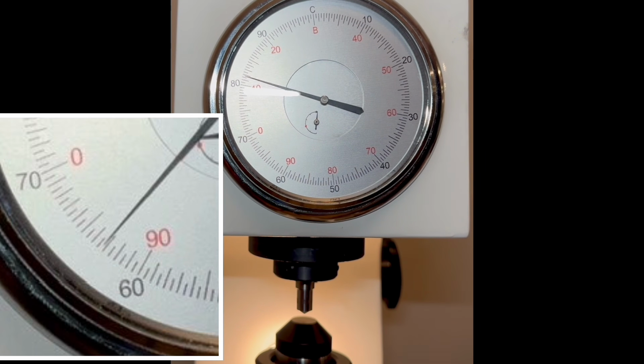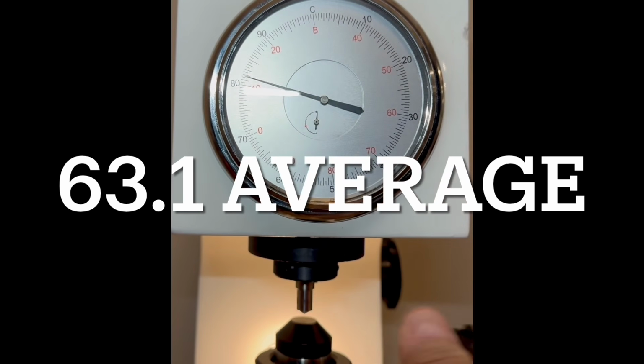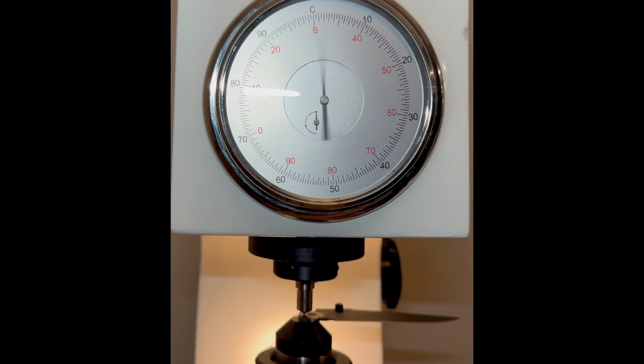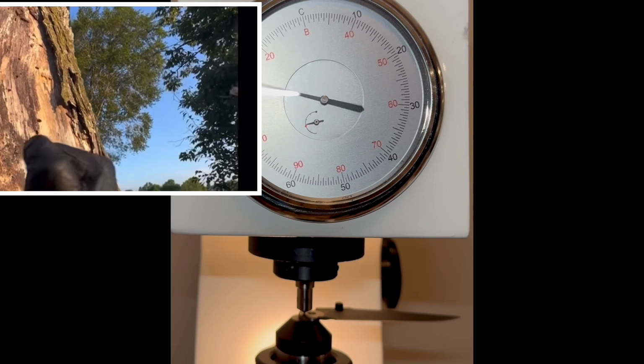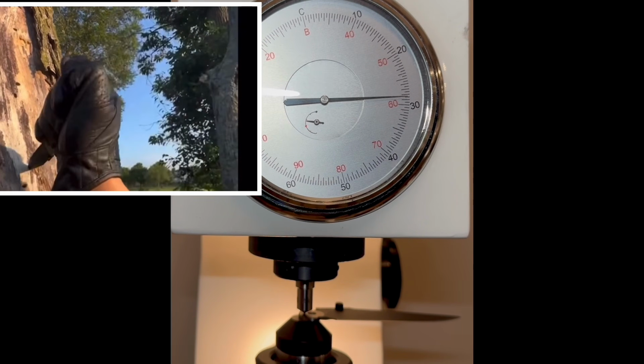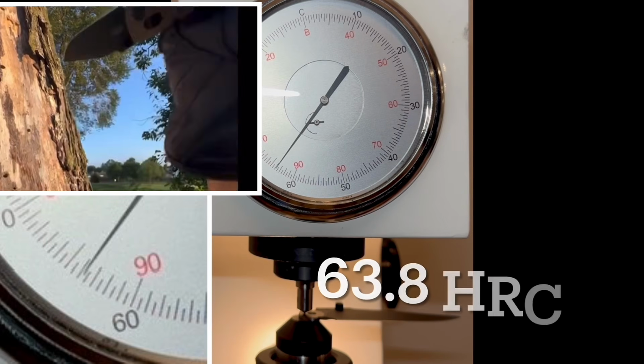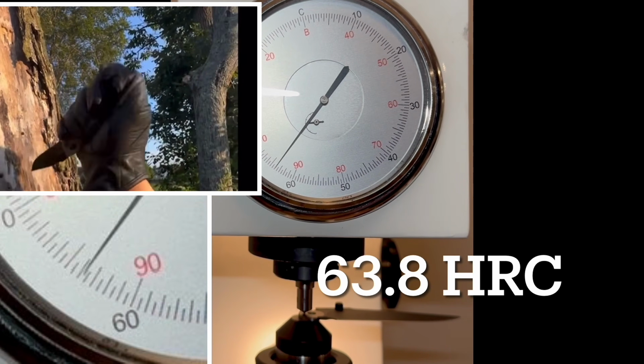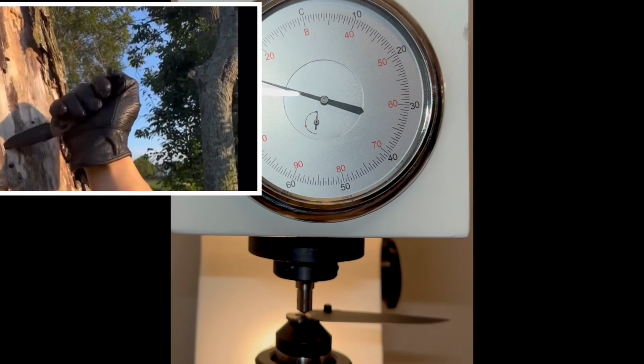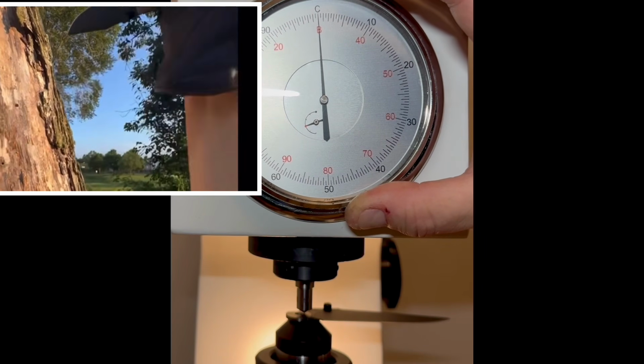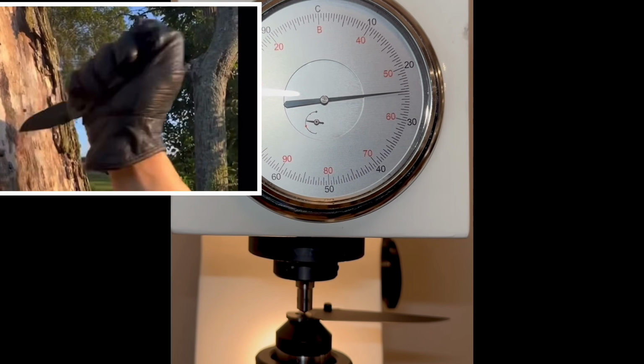At that time I was learning a lot about blade geometry, and that's why I got this blade, which was the second release of the Deca, and this one came with a clip point. And the clip point Deca has a swedge, and the swedge produces 2 ridges near the tip of the blade, and these ridges absorb a lot of stress. And so the first indentation yields 63.8 HRC, which is pretty darn high. And so even the thinnest of blades, when properly designed as far as the geometry goes, can withstand pretty high stresses.